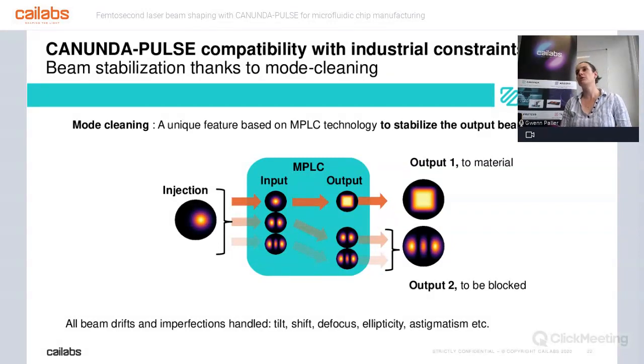At Cailabs, we have developed a very unique feature based on our multiplane light conversion, called mode cleaning, which helps stabilize the beam after the laser. How does that work? MPLC is based on mode propagation. When we design our MPLC, we propagate the modes of the laser one by one. When we see an injected beam which is shifted, what we see is energy inside the main mode, the TEM00, the Gaussian mode. This energy, we make follow a specific path, getting out of the module and delivering the proper shaping to the processing. Whatever energy is in the tilt, the shift, or other instabilities is considered higher order modes, and follows another path through the MPLC. It goes somewhere else and is blocked.